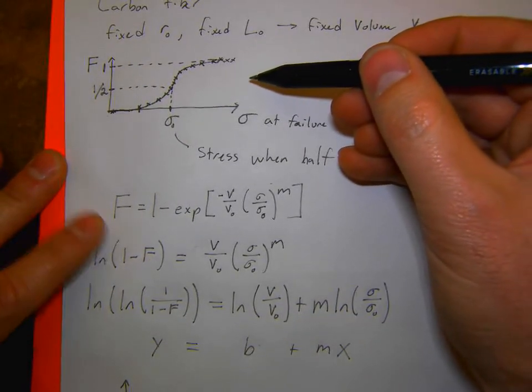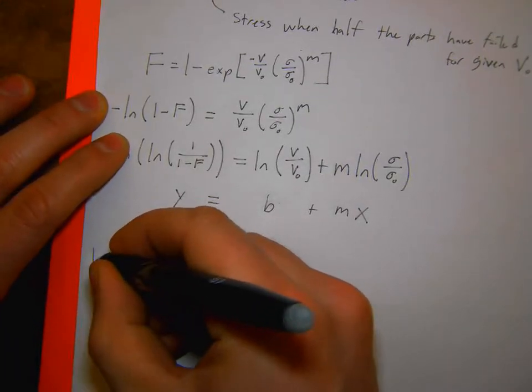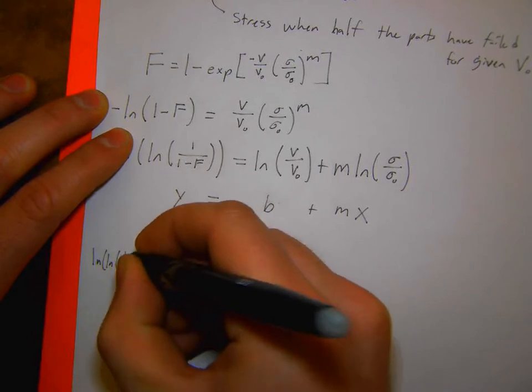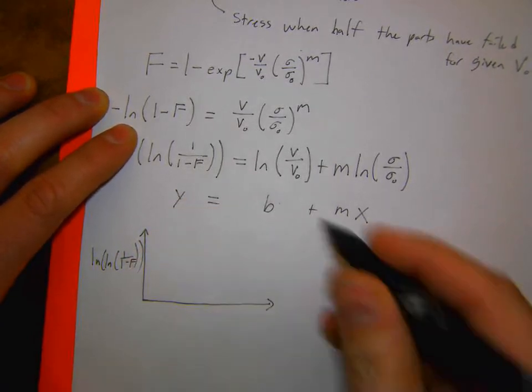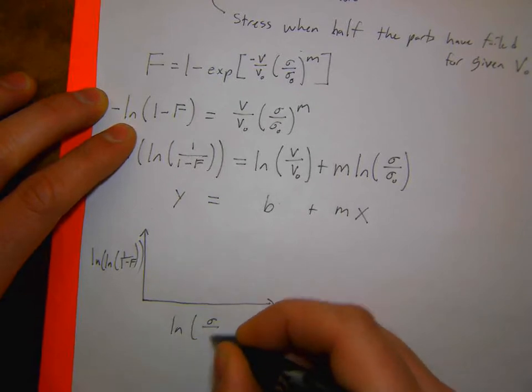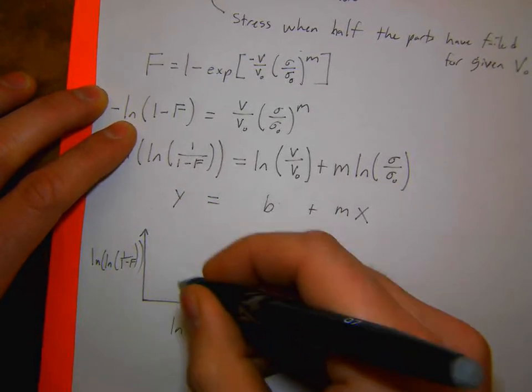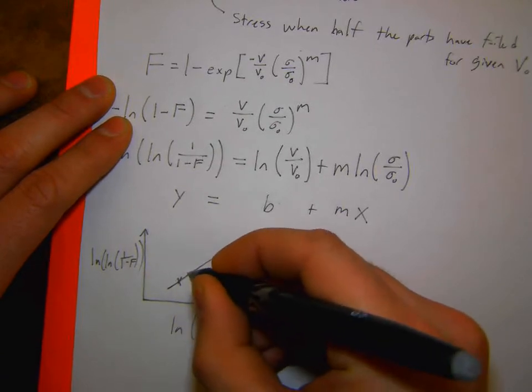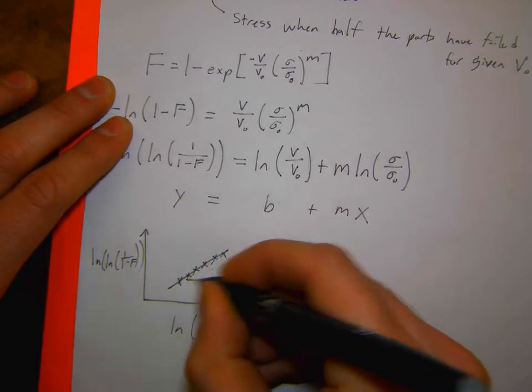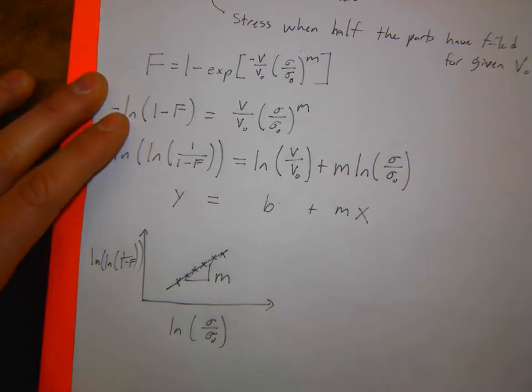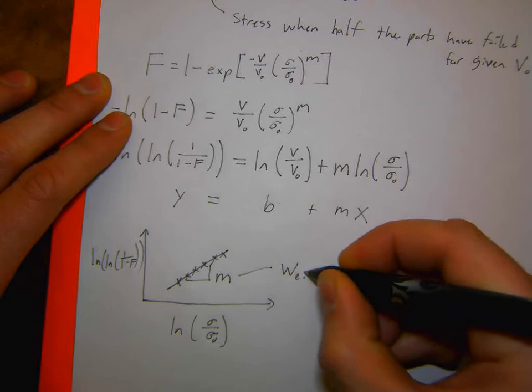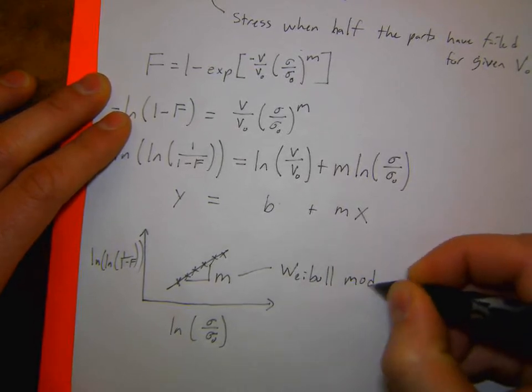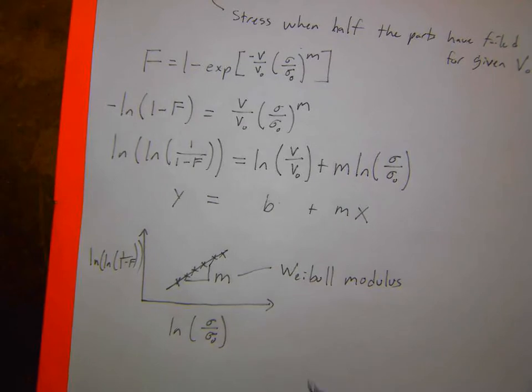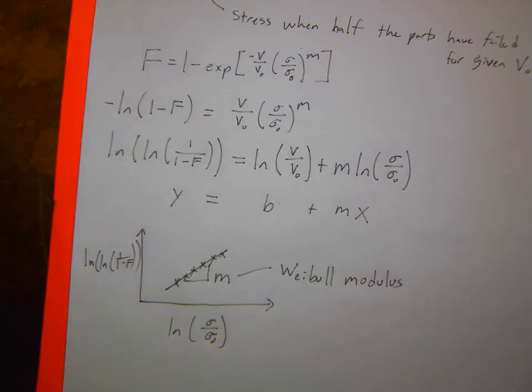and now I'm going to take this failure data that I had initially and rework it in terms of this reorganized equation. On my y-axis, I now have natural log of natural log of 1 over 1 minus F. On my x-axis, I have the natural log of sigma over sigma naught. And what I end up with, approximately, is something on a straight line with now a slope m. So this m is known as my Weibull modulus. And this defines effectively how random my part is.